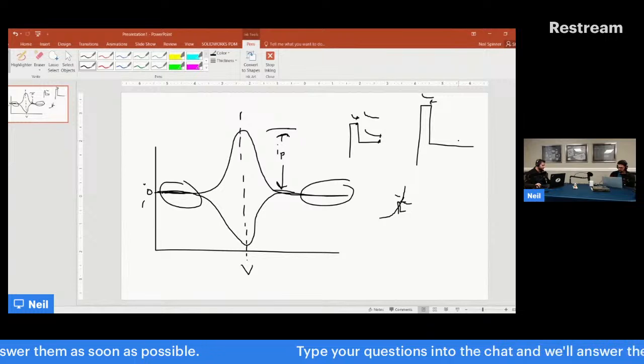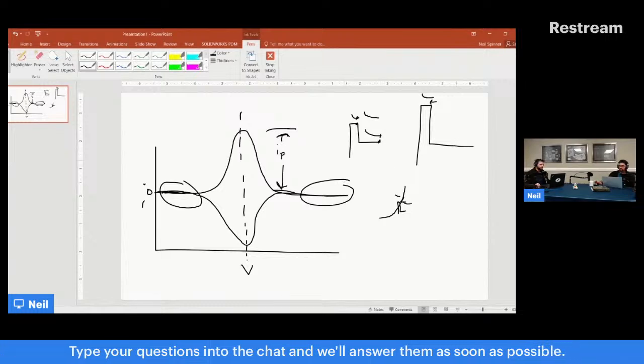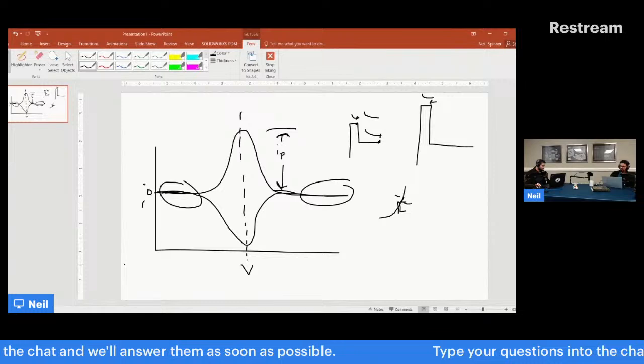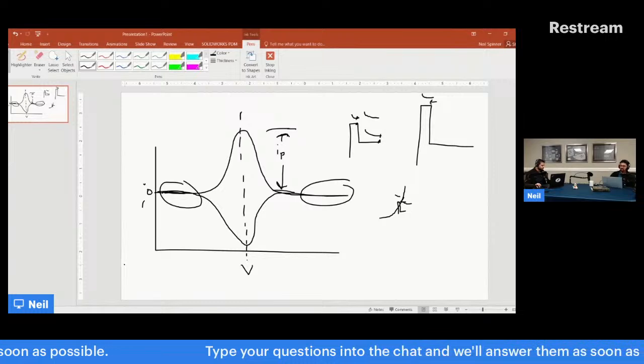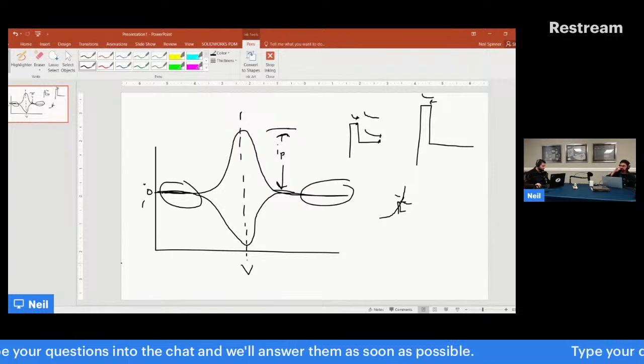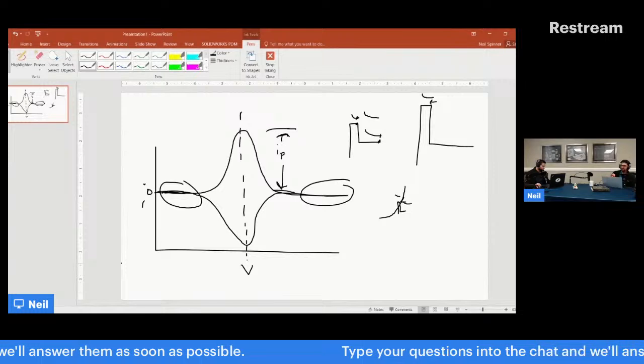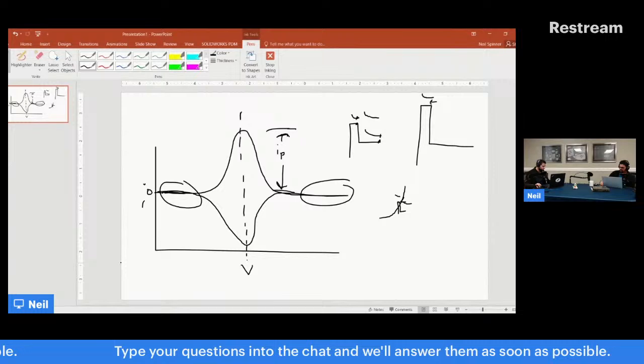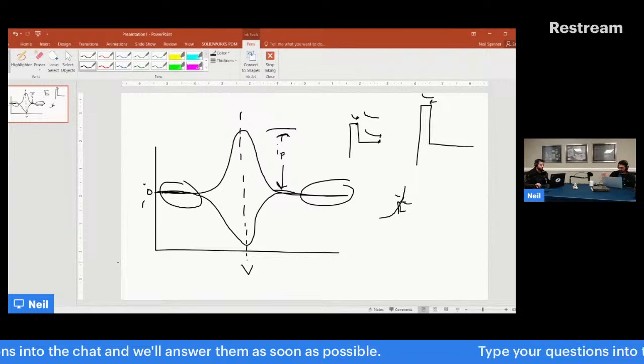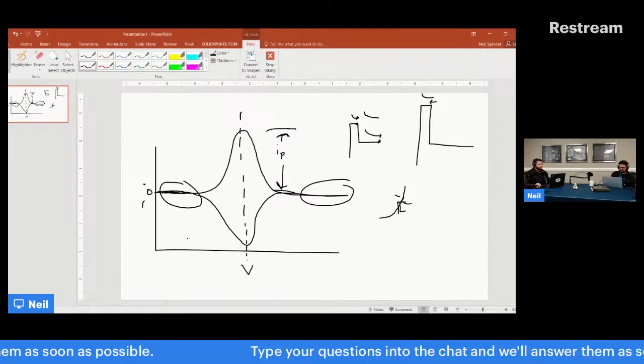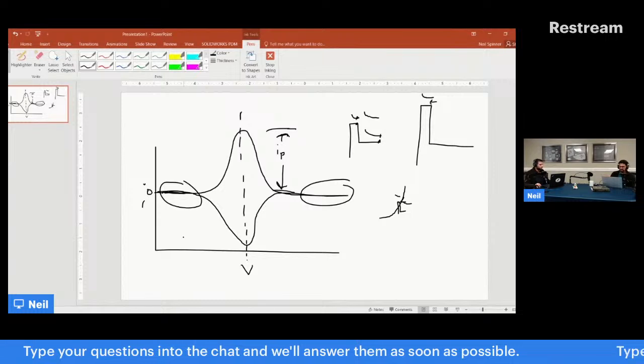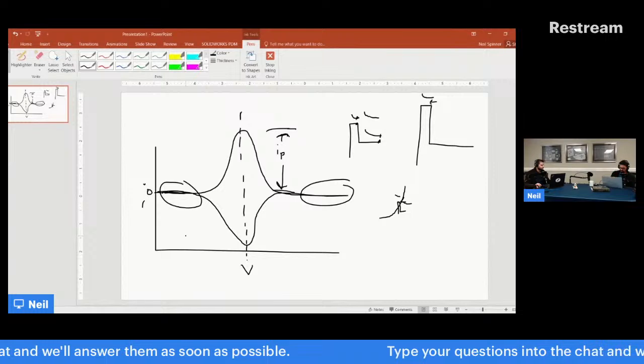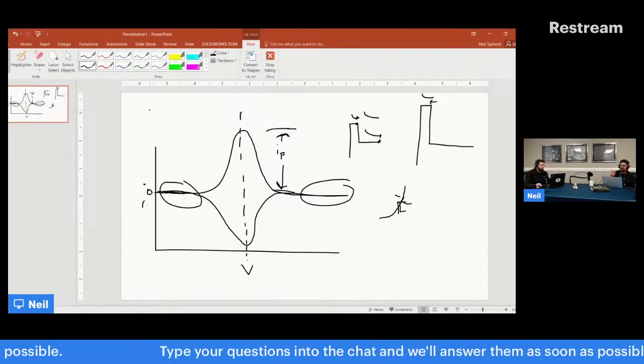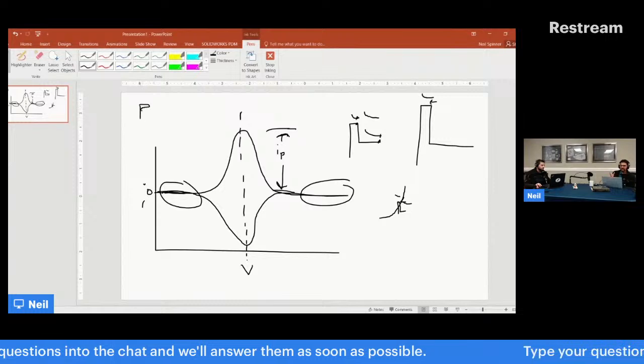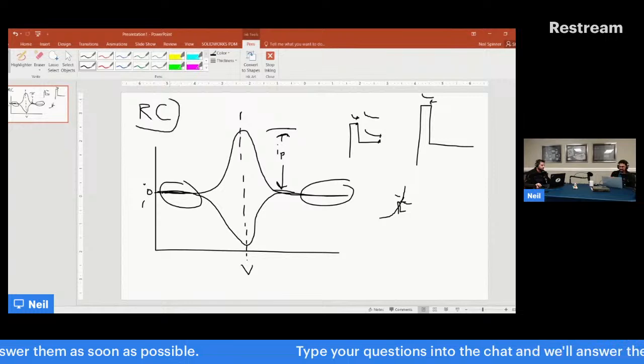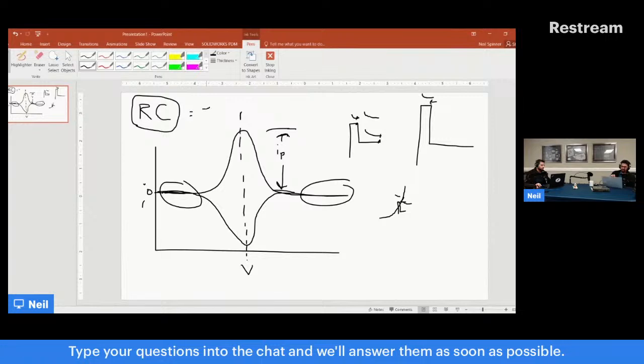There's actually a sweet spot in the middle of the pulse. When you first step the potential, you have a lot of background charging current. To completely charge the electrical double layer, the time constant is about 5 RC. That gets it to about 99.3% charged. Whatever your uncompensated solution resistance is, times the capacitance of your double layer, which is unique for your situation, sets the lowest limit for how fast you can pulse, because you're not going to want that data: you're going to have Faradaic current convoluted with double layer charging.